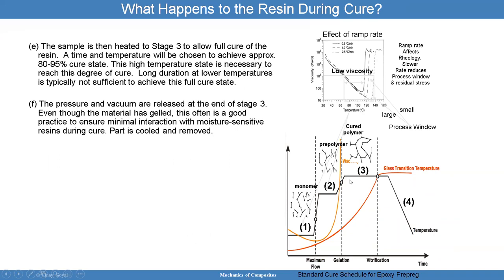And you need to come up with a time and temperature that will achieve 80 to 95% of the cure state. And you can see how I'm crossing that glass transition temperature. That's the glass transition temperature there. This high temperature state is necessary to reach this degree of cure. Long duration at lower temperature is not typically sufficient. If I just kept at stage two, that's not gonna help all the time.